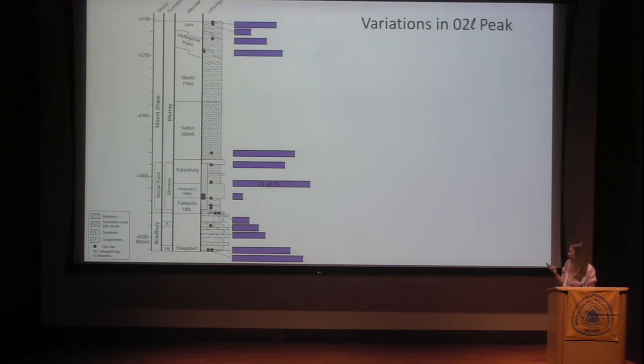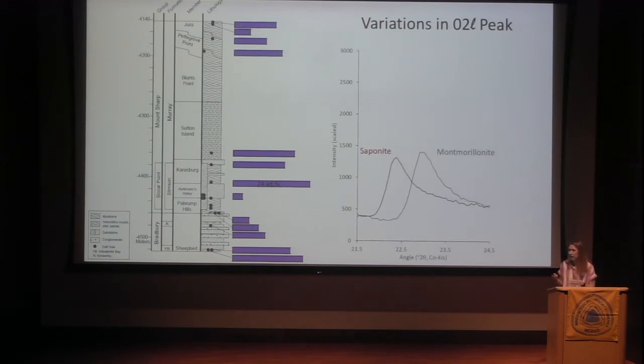Okay, we also see variations in the 02L peak within the stratigraphy, and this is a measure of the b-axis of the crystal, and it's telling us about the dioctahedral versus trioctahedral character of the phyllosilicate, where trioctahedral phyllosilicates like saponite have an 02L peak with a slightly higher d spacing than that of dioctahedral phyllosilicates like montmorillonite. So here I'm just plotting the 02L peaks from phyllosilicates from different parts of the section.